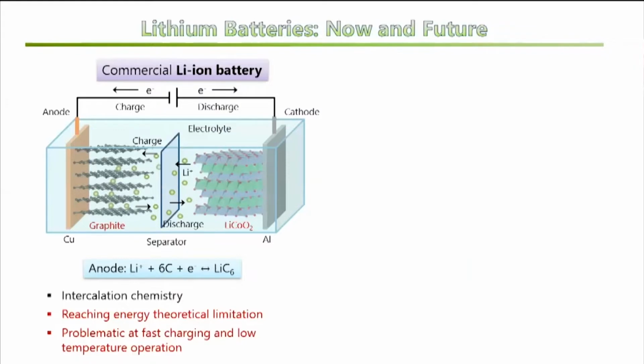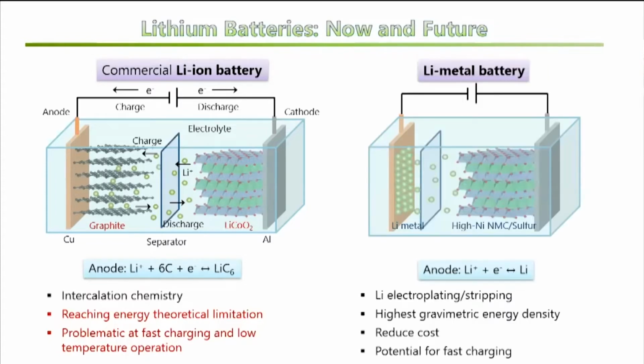Let's first look into today's lithium-ion battery. So inside of the battery, the lithium ions actually shuttle back and forth inside the battery, and the electrons go through the external circuit to provide electricity. So inside this lithium-ion battery, the graphite was used as the anode to host the lithium ions that come from the cathode side, based on a mechanism called intercalation chemistry, so that we can safely use our battery. However, this kind of intercalation chemistry using graphite is also the limitation for energy density, fast charging, and low temperature performance. In fact, just by simply removing the graphite, the battery can still function.